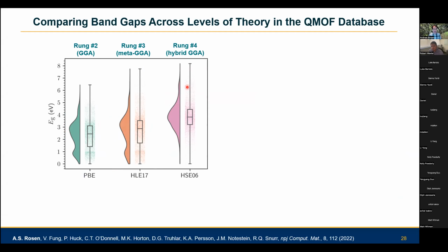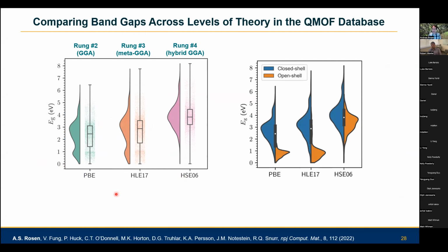We have this pretty much uniform distribution, and very different overall than the GGA level of theory, which is suggesting to me that there's not just an underprediction in PBE, but something drastically being predicted wrong in these lower levels of theory that can only be corrected when you have a hybrid functional with exact exchange. And the answer for why this occurs is actually quite simple.